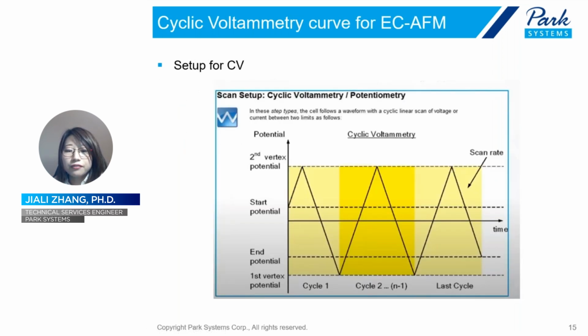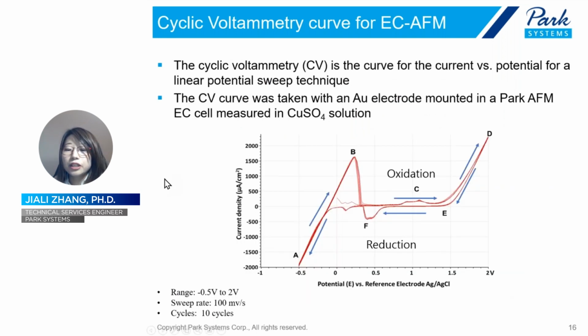Before we move to the AFM results, we have to sweep the potential and generate the CV curve of this redox reaction to find out the right potential to control the deposition or dissolution of copper. As we mentioned, by sweeping the potential back and forth, a reversible CV curve will be generated after a successful setup. As shown here, this sweep was run for 10 cycles, and you will see the overlapping is pretty good, so it means the reaction is reversible. Based on the CV curve, as the potential scans more positive from A to D, oxidation happens and copper dissolution occurs. While switching back from D to A, reduction happens and copper deposition occurs on the working electrode.